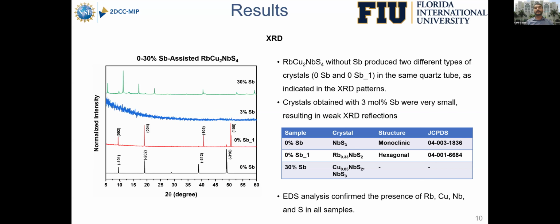The crystals obtained from 3 molar are very small, resulting in weak XRD reflections. And the 0% SB performs with the monoclinic crystal structure, whereas the 0% SB1 goes with the hexagonal. On the other hand, the 30% SB gives mixed phases of copper niobium sulfide and niobium sulfide. And the EDS analysis confirmed the presence of rubidium, copper, niobium, and sulfur in all the samples.